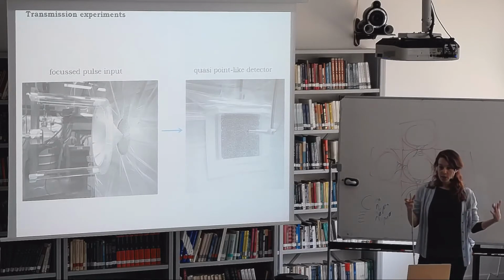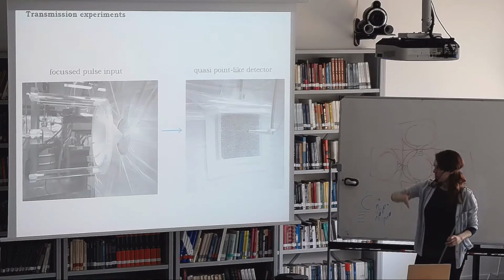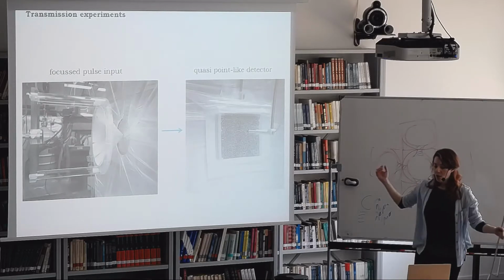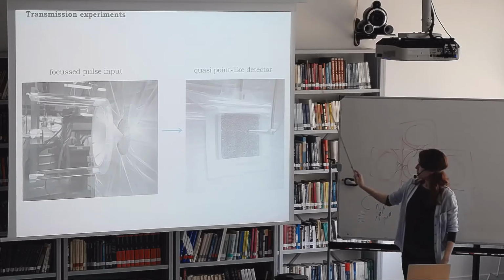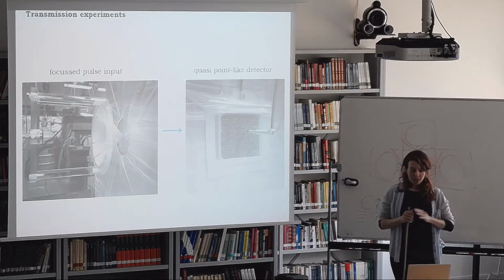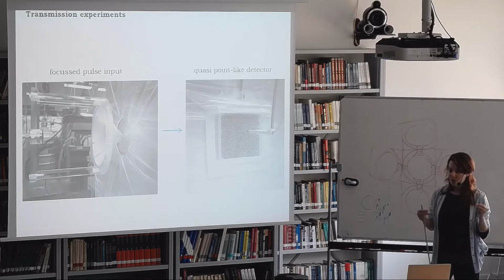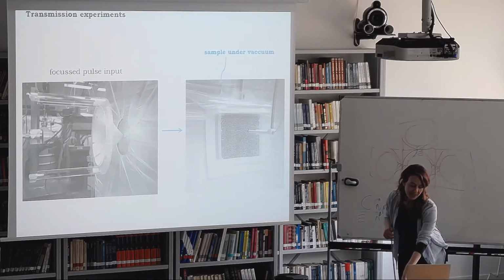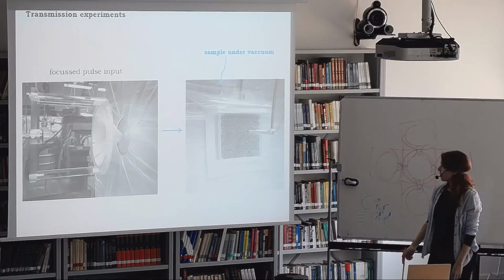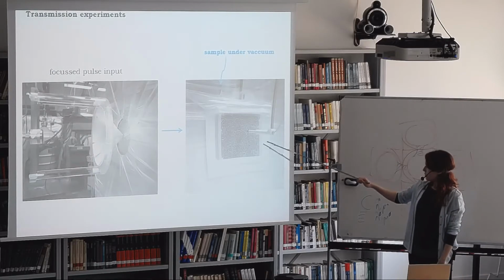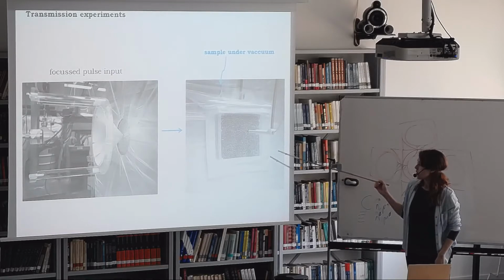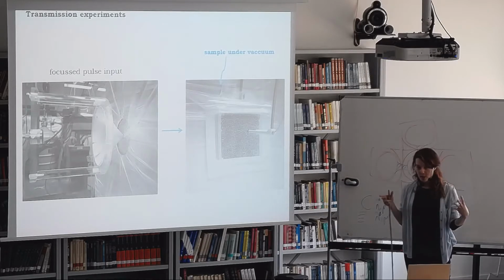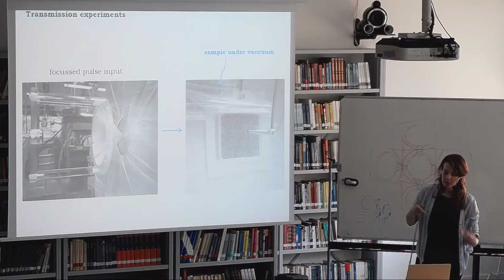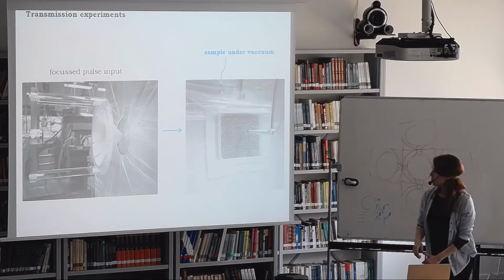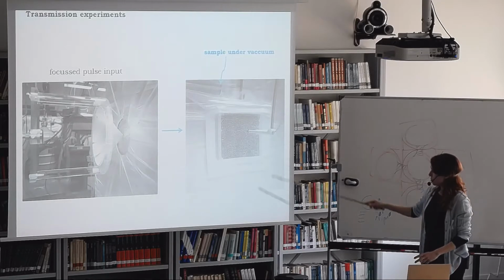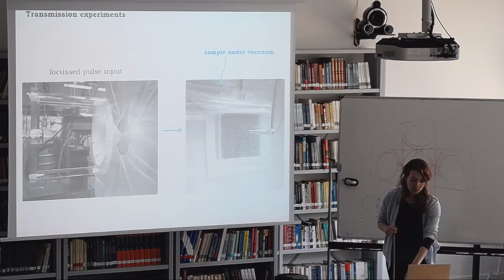Now we want to be really sure that we only detect what's coming through the sample, and so we essentially divide the water tank in two with a large sort of plastic baffle. That's this white thing that you see here, so that really we don't have sound coming around the sides of the sample, but it's only going from emitter to detector. And we vacuum out the air, which is between the pores of the metal beads, so that we have sound only coming through the aluminum network and not through the air in between the beads. Okay, so then we can move the sample around to average over many configurations of disorder.